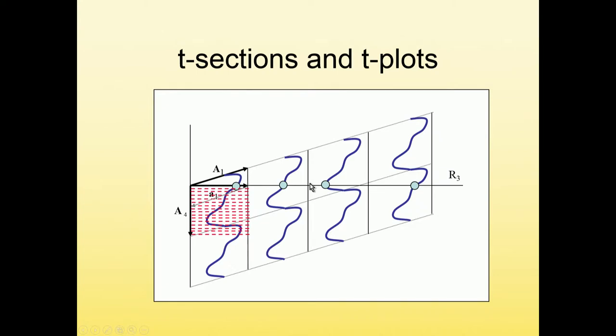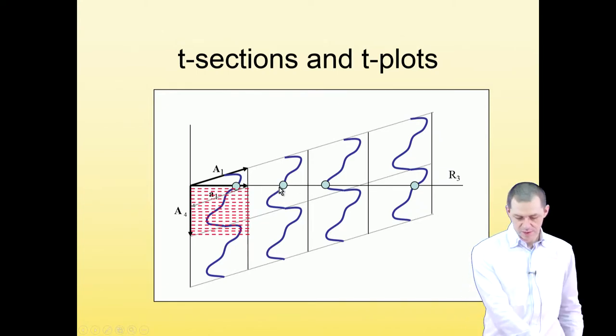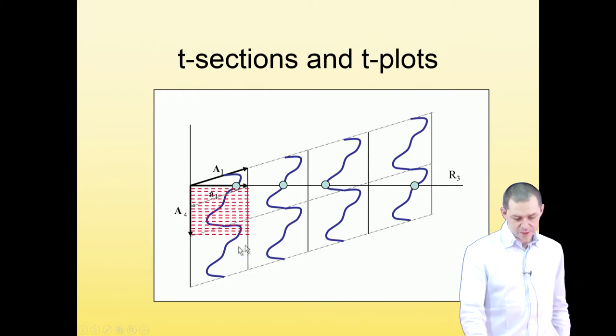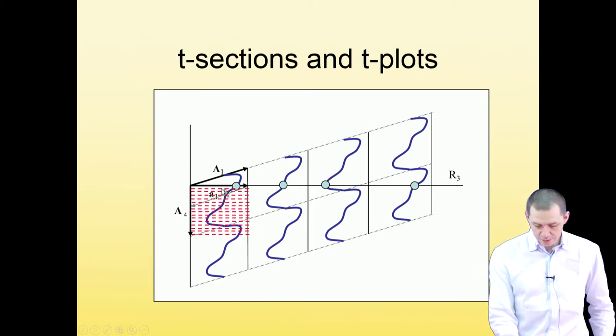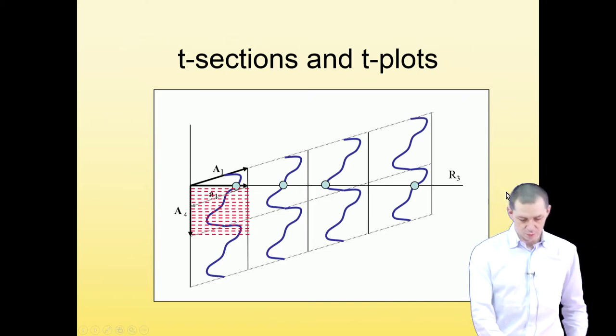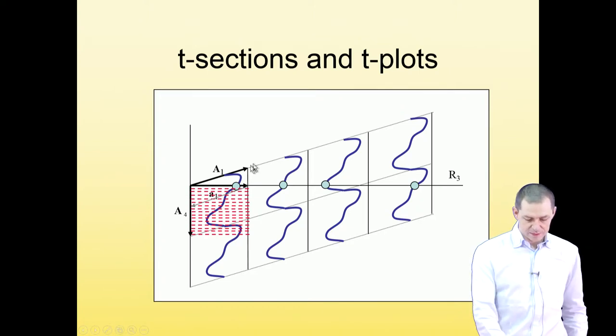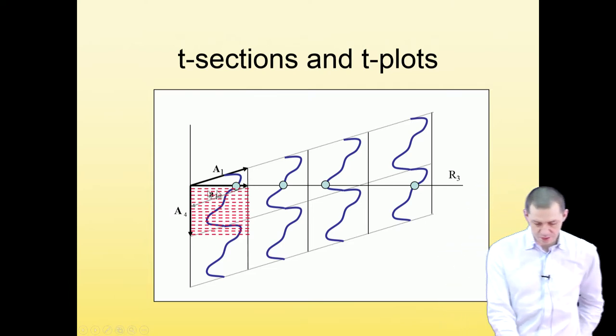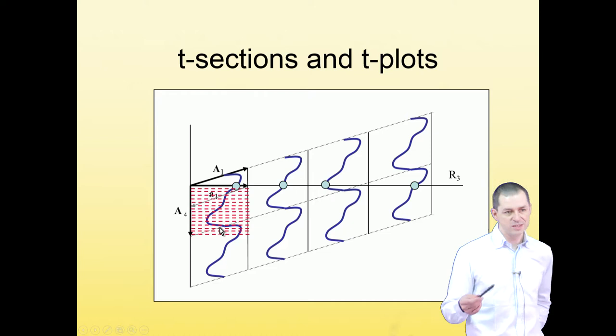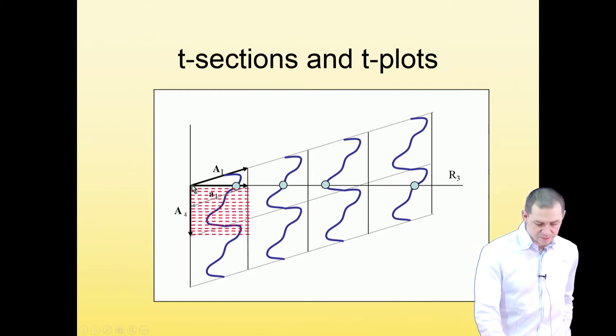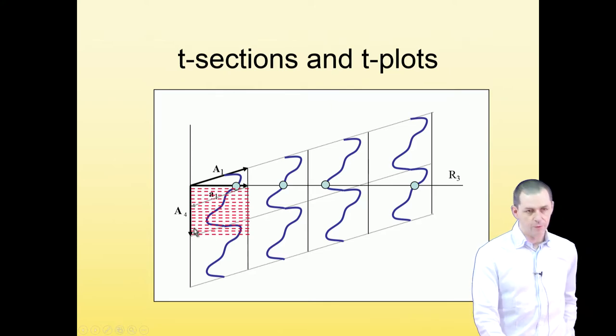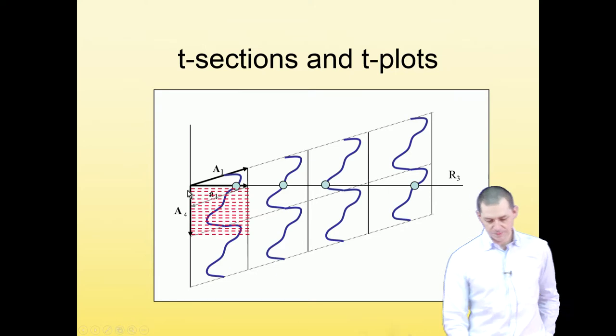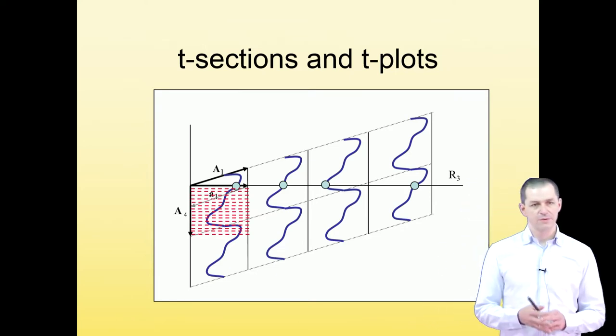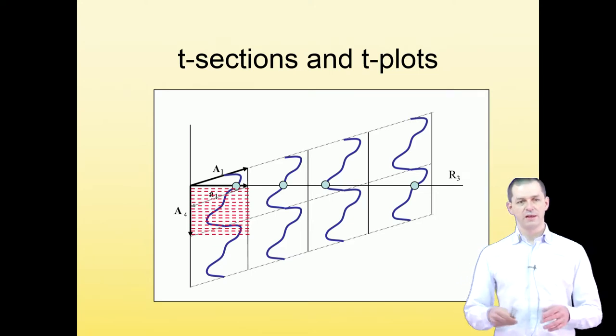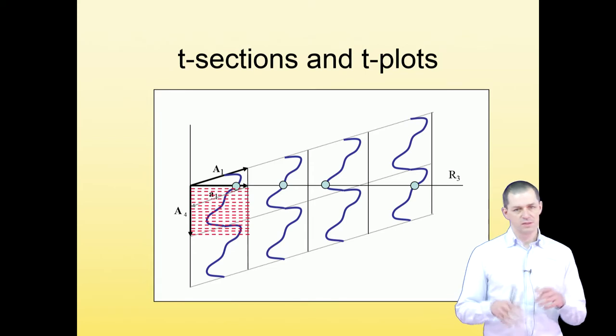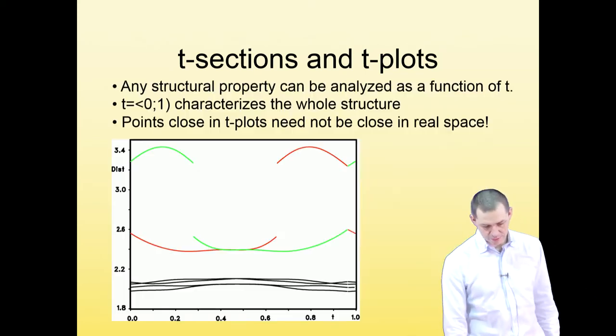And if we do this for all the unit cells, we can see that all these unit cells in the structure have their counterpart somewhere in the first unit cell, but we need to take sections that are parallel to physical space. So not sections that are parallel to the basis vector of the unit cell, but sections that are parallel to physical space. And these sections are called T-sections, and the coordinate that gives us the origin of that section along the vector A4 is called T. That's why it's T-sections. And you can plot any structural property as a function of this T, and get an idea what is the distribution of the property in the modulated structure.